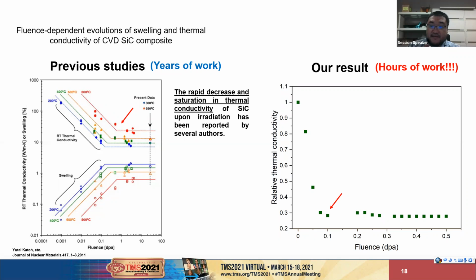Also, another feature that I want to emphasize is that the turnaround point is around 0.1 dpa, and we got a similar result, which validated our results as well. So it's proof that our technique works pretty well.